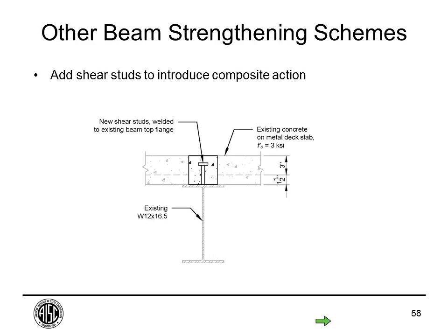Another strengthening technique that is pretty elegant when it can be done is to add shear studs. So if you have an existing beam, a concrete slab, and the beam is not composite or it's not fully composite with the existing slab, then you can add new shear studs that introduce composite action. This is done by creating discrete cores through the existing slab. You have to be very careful not to damage the top flange of the existing beam. Also, you'll need to be very careful about controlling the water that's used during coring. Make sure that that is not going to damage the space below. But if you can do this, then it's usually a good solution, because you don't need to have access to the underside. The strengthening can be done from the top side.